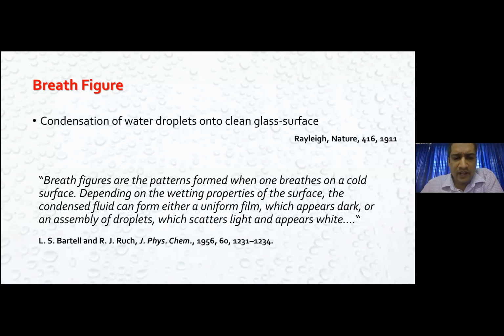The subsequent work carried out by Bartell and Ruch focused on one conclusion, that breath figures on a cold surface, depending upon the wetting properties of the surface, can be condensed to form a uniform film which appears dark in an optical microscope, where they tried to do the measurement at a very close, low angle. And the other possibility is to form an assembly of droplets, and this assembly of droplets results in scattering of light, and the surface appears to be white.